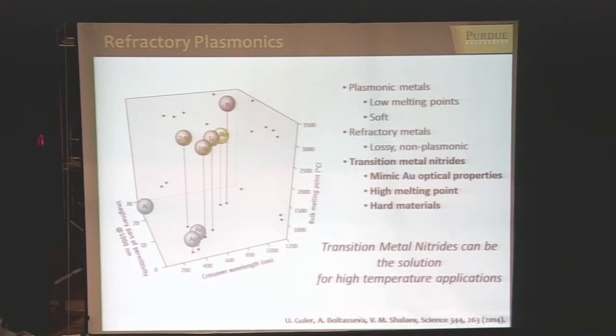When we look at these properties—the ability to sustain high temperature—we could place these plasmonic materials on a plot showing the wavelength at which epsilon becomes negative, meaning the material becomes plasmonic, along with the imaginary part, basically losses, and the melting temperature. If you look at silver and gold, the materials largely used for plasmonic applications, yes, they are plasmonic in the visible, meaning epsilon prime is negative, but the melting temperature is very low in bulk, and when nanostructured, even 400 Celsius is a problem. Tungsten is a well-known refractory material, but it's not really plasmonic—it has very poor, if any, plasmonic properties. In contrast, the materials I'm discussing now, transition metals or plasmonic ceramics, actually have plasmonic properties with epsilon negative, and very high melting temperature.